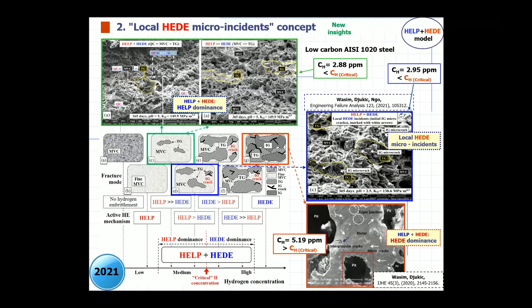This is the confirmation of this concept, published in 2020 with Dr. Wasim from Australia. We show here, as you can see in yellow, we have local micro HEDE incidence in the form of transgranular failure. We have a predominance of ductile failure due to microvoid coalescence, but we have HEDE microincidence. And when we have a high enough accumulation, the blue one, as you can see, we have predominance of transgranular failure and appearance of intergranular brittle failure. We have a high hydrogen concentration, but still HELP is predominant. And when we have a hydrogen concentration above the critical hydrogen concentration, 5.19 ppm, we have a full HEDE dominance, but still we have remaining signs of ductile failure due to minor incidence of HELP. So we have a change of the participation of HELP and HEDE incidence in our material.